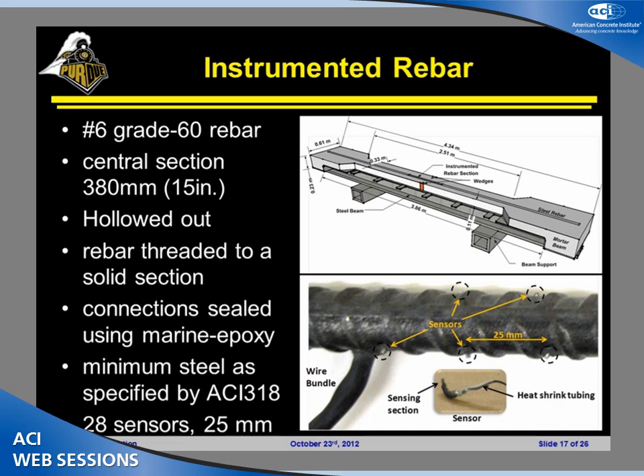So, as I mentioned before, it's an instrumented rebar. What this means is we've taken a number 6 grade 60 rebar. We've essentially put that into the center section, and we've threaded the ends. This 15-inch section of the rebar has actually been hollowed out, so we've drilled out the center portion of that rebar, and we've placed in these different small sensors that will be ground so that they're flat on the surface, and we can monitor the corrosion at those particular pins, so we can see how far back away from the surface that corrosion is starting to take place.